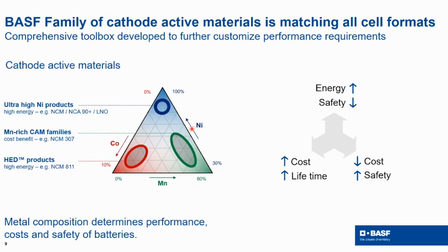Every cathode material needs lithium. However, the performance of the material heavily depends on the mixture of the other metals, the cobalt, the nickel, and the manganese. And all these three elements bring different aspects to the battery. So we are today heavily in that red area, the high energy NCM materials with 80% nickel, 10% cobalt, and 10% manganese. The trend is to go to high nickel that increases the energy density and therefore also the performance of the battery. To manage the cost, manganese is also added, and the manganese rich families are attractive in that area.